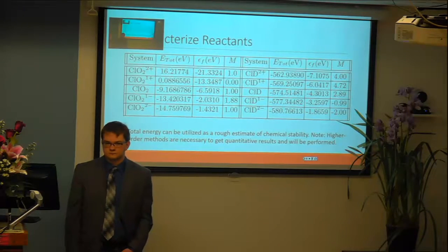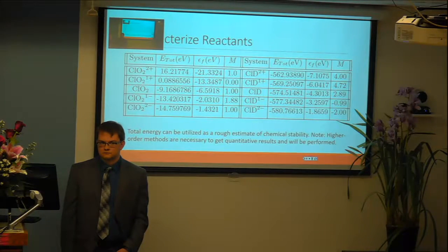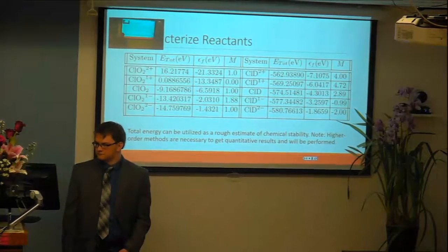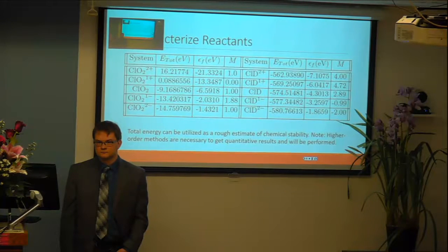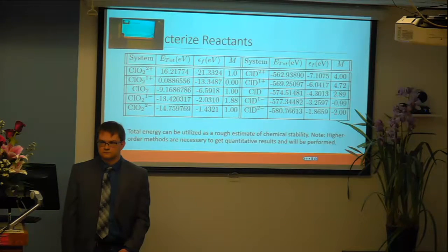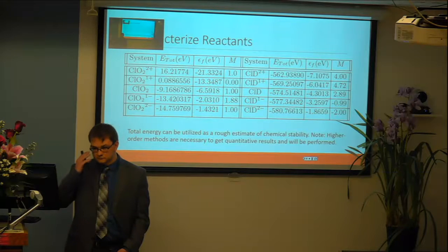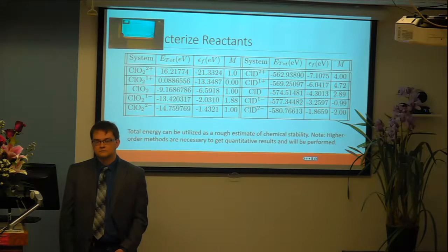So one way to do that would be to correlate the ClO2 minus to the change between the ClD, where this is going from -1 to 0, and the -1 to -2 over here. Then you can see what the total energy change is when you do that electron transfer, and that can give you a good idea of what's going on. Typically, you would use ferrocene for this, because if you reference to ferrocene, it's very good. You can compare it to experimental data.